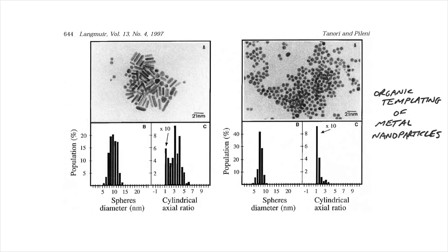After subsequently drying or burning away the organics and moisture, one is left with tiny nanoparticles that have taken the shape of the micelles they formed in. Although the formation of the particles themselves is often a non-equilibrium process, the self-assembly of the micelle template is predictable by equilibrium and can be used to control the size and shape of the particles over some range.